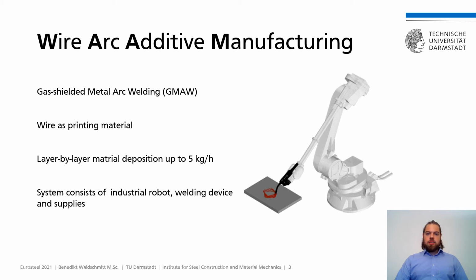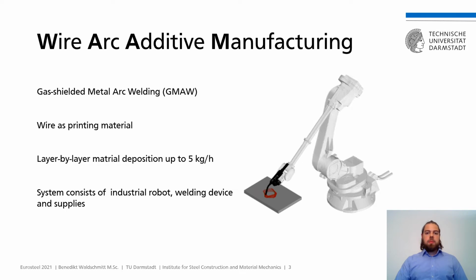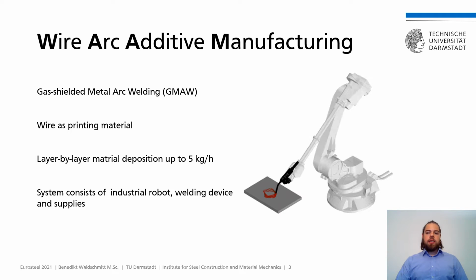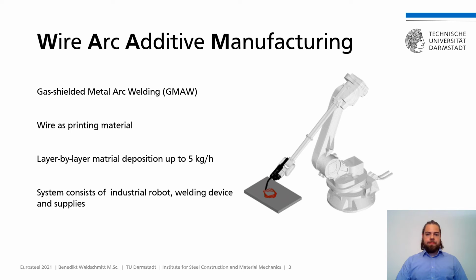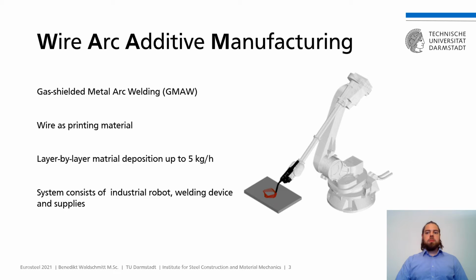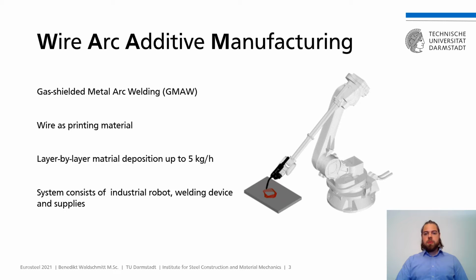The first question is, what is WireArc additive manufacturing? It's an additive manufacturing process based on gas-shielded metal arc welding. With a high build-up rate up to 5 kg per hour, WAAM offers the possibility of integrating additive manufacturing into steel construction. The wire electrode, e.g. carbon or stainless steel, forms the printing material, which is applied in layers. A system consists of an industrial robot with up to 6 axes and a connected welding device plus corresponding supplies. The right-hand side shows a layer-by-layer material application which extends vertically.